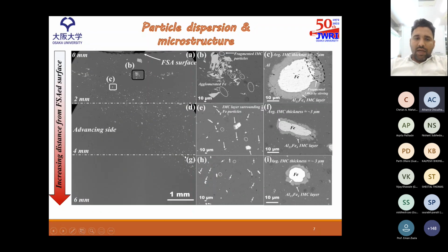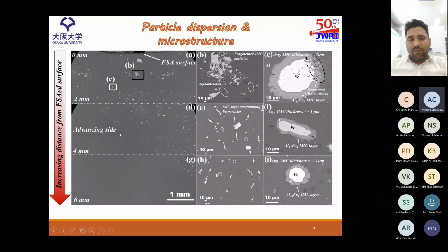We have also conducted some high magnification SEM micrography to evaluate the nature of particle dispersion. And this is the advancing side on the top. We can see that there are some agglomerates of the particles. These agglomerates can also be visualized in some high magnification micrograph here, whereas in the middle and in the bottom section, the particles are homogeneously distributed.